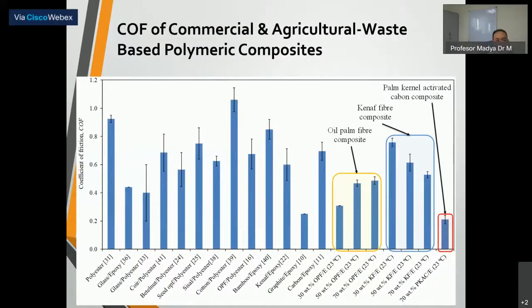Okay, here we compare our agriculture-based composite with other agriculture-based polymeric composites and also the commercial composites. You can see that this is the palm kernel, this is the kenaf fiber composite, and this is the oil palm fiber composite. I emphasize that this friction coefficient of palm kernel activated carbon is at room temperature, because at high temperature, the coefficient of friction and also the wear rate increase. So at room temperature, the friction coefficient of the palm kernel activated carbon is similar to graphite.